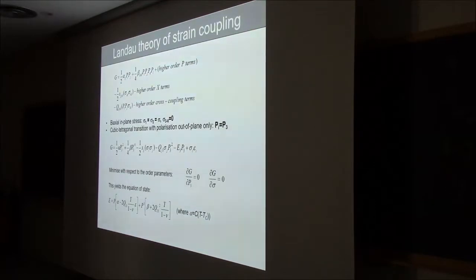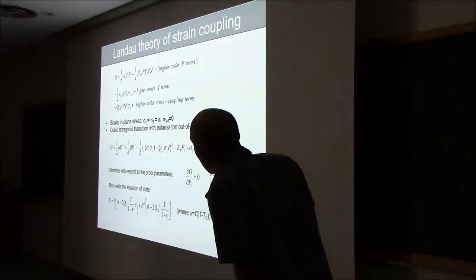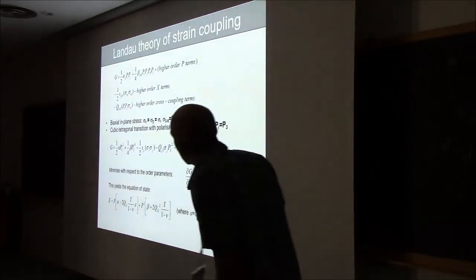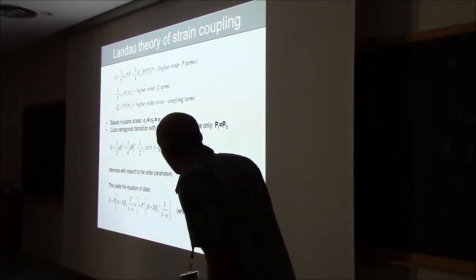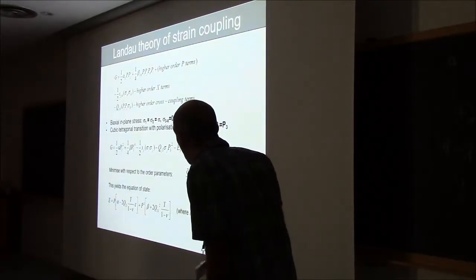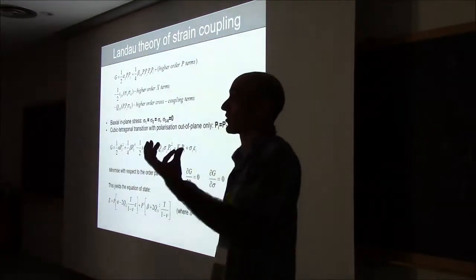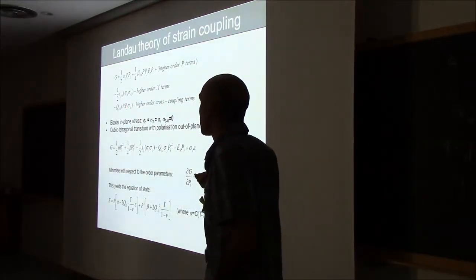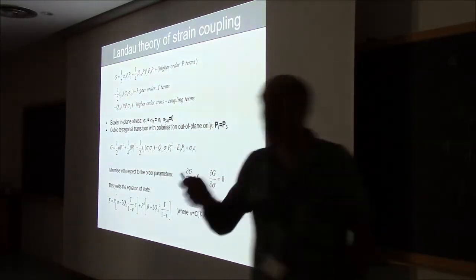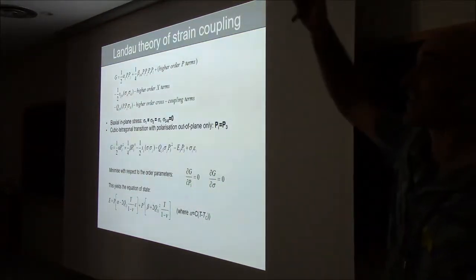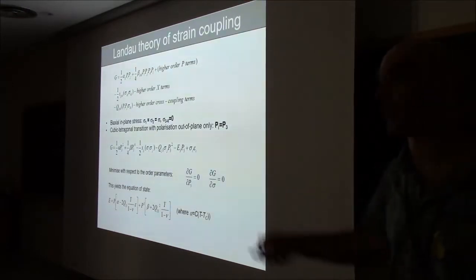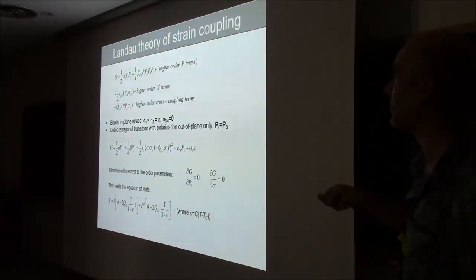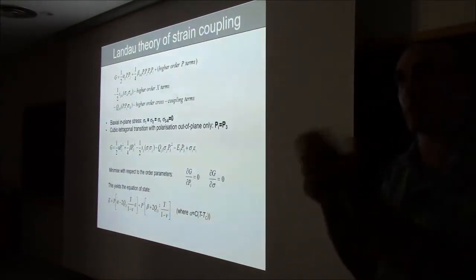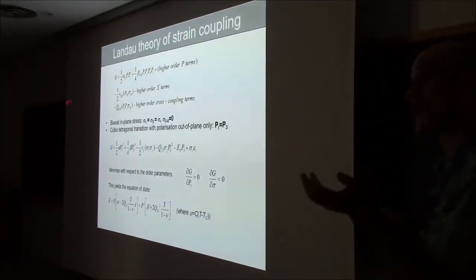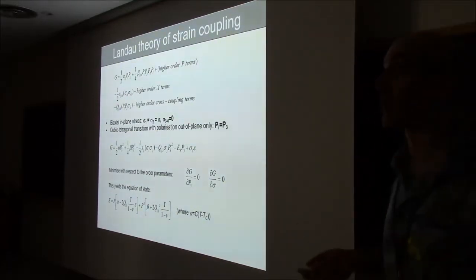Okay. Then, okay, so that's just the polarization. You can then add the stress or the strain and the coupling between the stress, in this case, sigma, and the polarization. And for perovskite ferroelectrics, the lowest coupling term that you can include is strain or stress times p squared. Okay? And remember, it has to be p squared because it has to describe also the high symmetry phase of your material. You think, okay, if it's a piezoelectric material, I should be able to put p times sigma here, so polarization times strain here, linearly coupled, as you would expect in a piezoelectric. But your free energy has to also describe the cubic phase, so the polarization has to be squared.